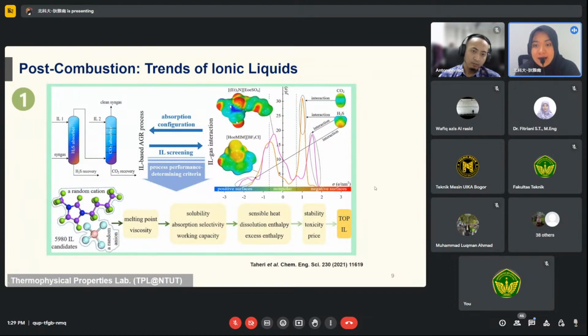Like here, the ionic liquids, you have the complex molecular structure here, and then you can see the negative surface, positive surface in here, and how they interact. Is it that they have positive surface together or negative surface together? So it means that we would like to check the possible interaction between CO2 and the sulfuric gas with our ionic liquids. Then after we get the prediction, we could synthesize our ionic liquids and try to check the CO2 capture or CO2 solubility in the ionic liquid.